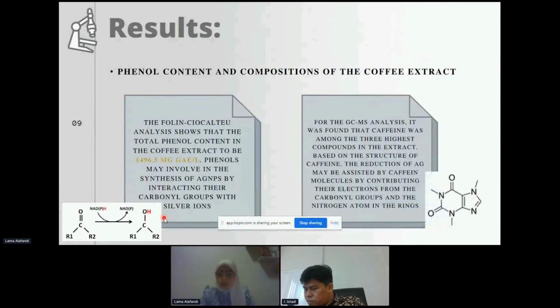Moving to the GCMS analysis, it was found that caffeine was among the three highest compounds in the extract. Based on the structure of caffeine, the reduction of silver may be assisted by caffeine molecules by contributing their electrons from the carbonyl groups and the nitrogen atom in the rings. Furthermore, it was found that caffeine also can function as a capping agent in the synthesis, and the presence of rings improves the stabilization of silver nanoparticles and prevents conversion to silver ions again.